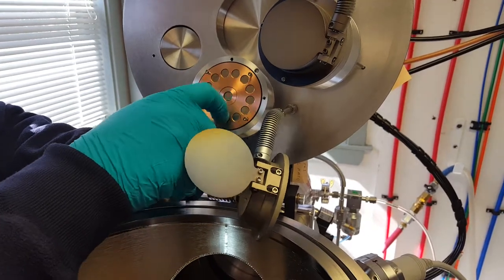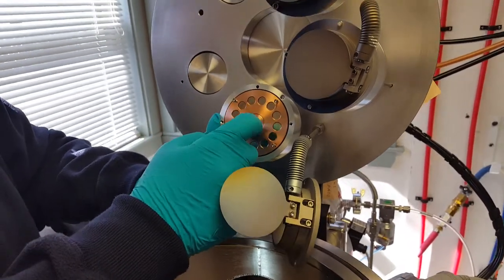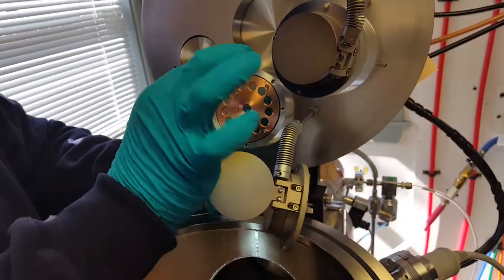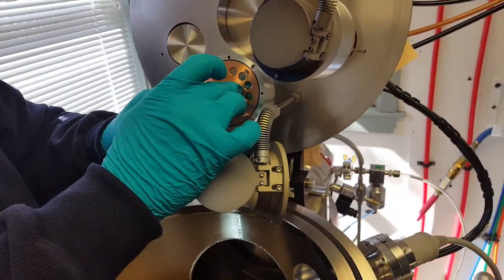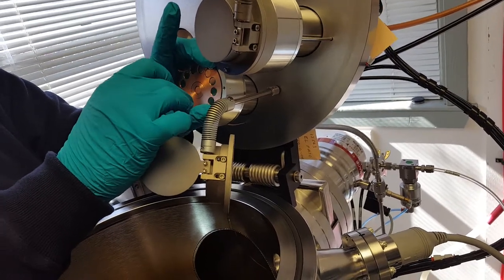This stack of three magnets in each hole. We just need to remove the center stack. Then we have a big open hole here so we use an iron slug and put that into the hole and that just reconfigures the flux field to be more appropriate for your magnetic material sitting in front.